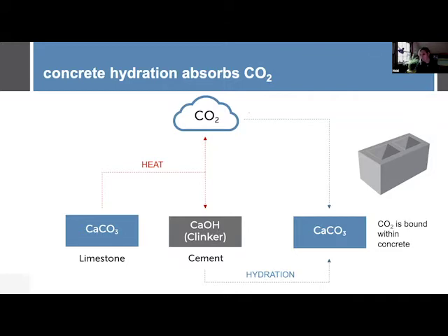This has historically been called carbonation, like I mentioned, and about 40 to 50 years ago it was studied extensively due to corrosion issues with rebar in the concrete, because as it carbonates, its pH decreases. So corrosion protection requirements for masonry and concrete have been figured out for the most part and are part of building code requirements that haven't changed for about 50 years. But studying and researching carbonation, AKA carbon sequestration, for environmental reasons is fairly new territory within the industry.